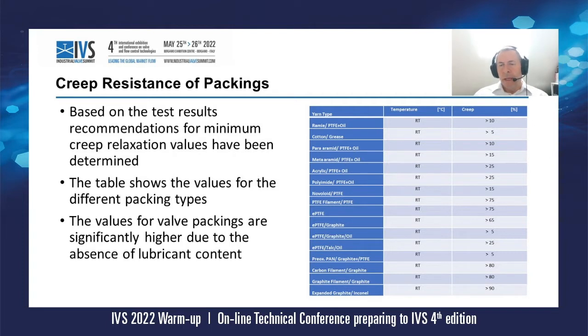For the valve packings we have significantly higher values, which really start for PTFE with creep values bigger than 75%, or for carbon filament values bigger than 80%, and with expanded graphite reinforced with Inconel we have values even bigger than 90%.